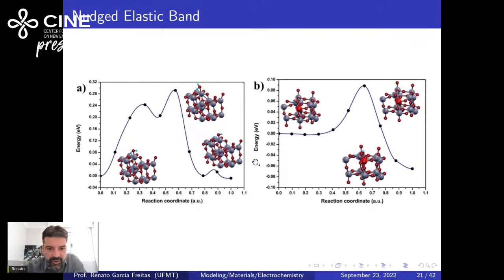Yeah. So it was impressive, this result. Take a look here. We have the anatase, and we have all images obtained here. Here, the doping one from anatase, and here we have almost two main determined reaction steps, like in this part, 0.34 electron volts of activation energy, and this one from the transition state, we have almost 0.3. It's a very large value, 0.3, only for anatase, pure titanium dioxide. And here for titanium dioxide iron doping, we have a decrease to less than 0.1. As you see here, take one image, the first image and the last image, the initial state, the final state, the transition state, and we don't have several steps like in this case.